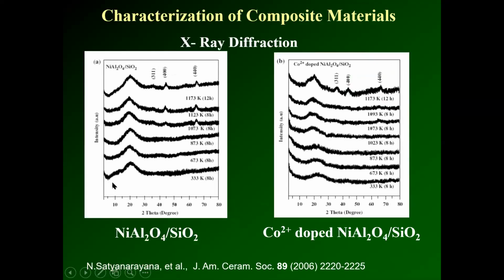You can see that I have not given the IR, but XRD is enough for this. We have taken the XRD for every stage. The sol is prepared at 60 degrees centigrade, or 333 Kelvin. When you take the XRD of this one, it is amorphous. All are in ionic state, whether it is silicon or oxygen, nickel or aluminum. So you don't see any solid structure in this. Increasing up to 800 degrees centigrade or 1073 Kelvin, this complete gel is amorphous.